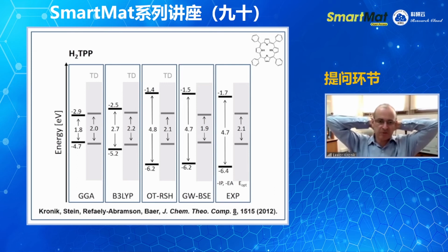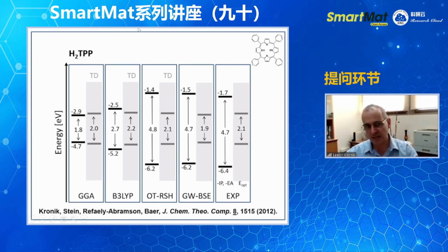For example, if you optimally tune something like B3LYP, typically you see that the prediction is that you need something like 80% of exact exchange to get the ionization potential theorem correctly. Now, okay, you got the ionization potential theorem correctly because you insisted on it, fine. But we know that with 80%, bond lengths and thermochemistry and energetics, all that is going to be awful.